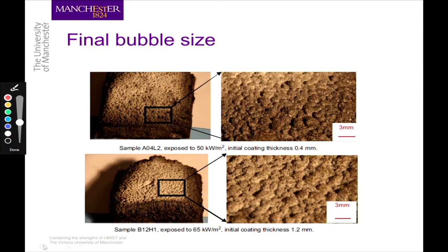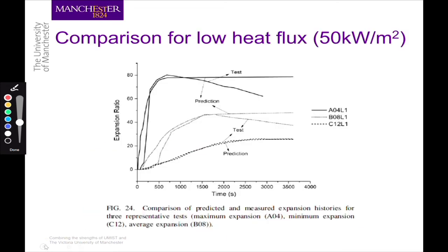Expansion stops at some time, and when it stops, some bubbles are produced, and we need to know the bubble size in order to relate it to the thermal conductivity of the material. And we have found 3 millimeter is about the final average bubble size. So with these assumptions, we have predicted the thermal expansion, or the expansion, of intumescent coatings as a function of temperature, and these are our results